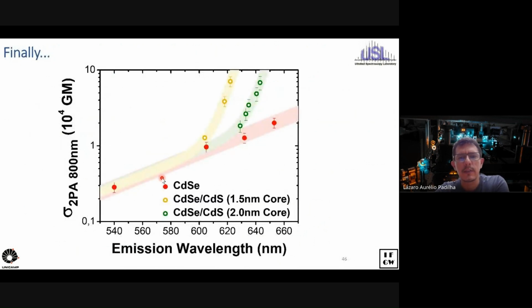So we can close this by simply putting together the data for the dot-in-rod with our chart that we have for the core shell and core only, and see that there is a very good enhancement, also the volume normalized, or I'm sorry, for the two-photon absorption cross-section compared to a regular quantum dot at the same wavelength.